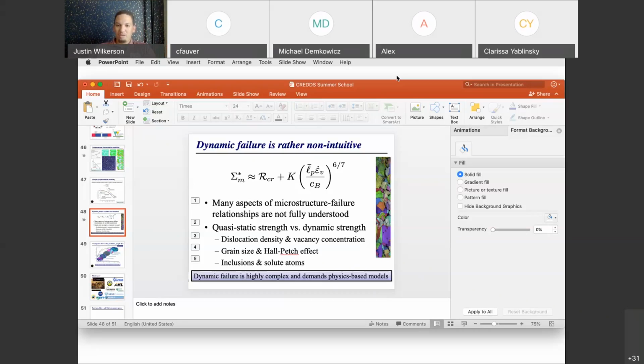So what you would prefer to do is to somehow catch those fragments, and that can be done. There are various recovery mechanisms. You could have the fragments go into some soft gel or some kind of soft material that hopefully doesn't provide any additional deformation of those fragments. But I agree with you that there definitely could be, and most likely are, differences in the fragments that are formed from the front side versus the back side. And there are also differences in the spatial location where the fragments come from. Do the fragments come from right underneath the projectile or from farther away from the projectile? All of that is always interesting to study.